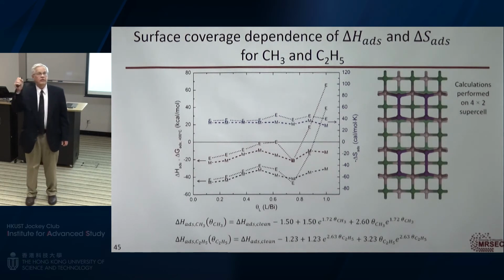And so one of the things that we find out is that while the film is growing, if I'm using trimethyl bismuth, so bismuth with methyl groups on it, it actually terminates the surface. The lowest energy, or this is the free energy, is when every bismuth atom is on the surface, and all the bismuth atoms have a methyl group on. And so that'll look something like this, in a cartoon form. All right, so that's what's happening during growth.